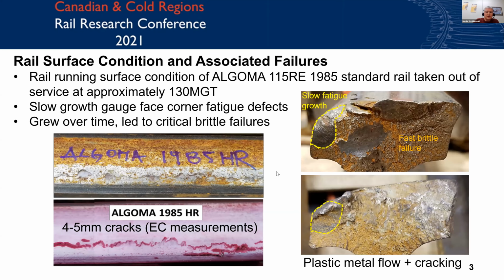So for the rail surface condition, the rail that we got in the lab was, as mentioned previously, an 85 Algoma type of rail. At the time that this rail was installed in track, this was a pretty good grade of rail. It was considered standard rail grade. And obviously, over the last 30 years, rail technology has progressed to a point where better rails are available right now. They have better microstructures, better mechanical properties, and therefore are more prone to withstanding higher stress levels, which leads to fewer failures. Nevertheless, at the time when this rail was installed, this was a fairly good rail grade.